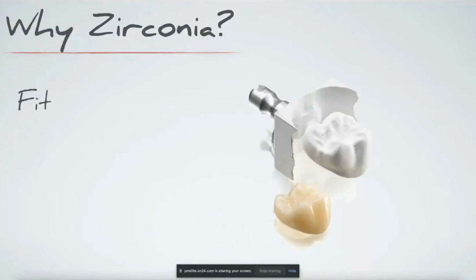And so because it's such a large restoration when it's milled out, and because zirconia pre-sintering is such a soft material, almost chalk-like, it's very easy to get very fine, very detailed margins. It doesn't get chippy along the margins like some of the glass ceramics do when they're milled out. And there is no other way to manufacture zirconia than milling it. So, when I talk to doctors and they tell me they like zirconia, I say, well, you like CAD-CAM. You like CAD-CAM type of restorations because that is the only way that we can design these. And the fit is very intimate.